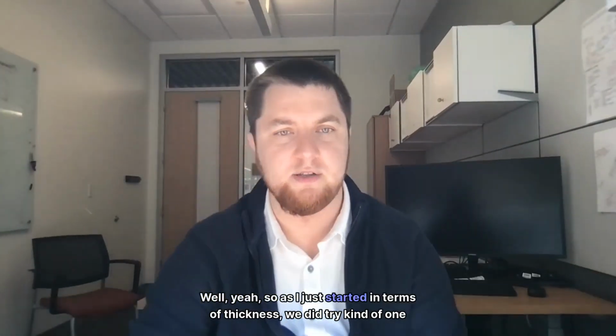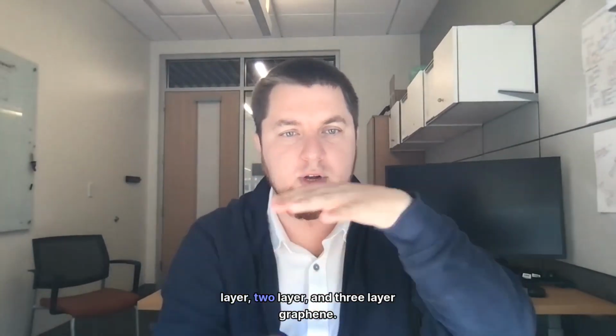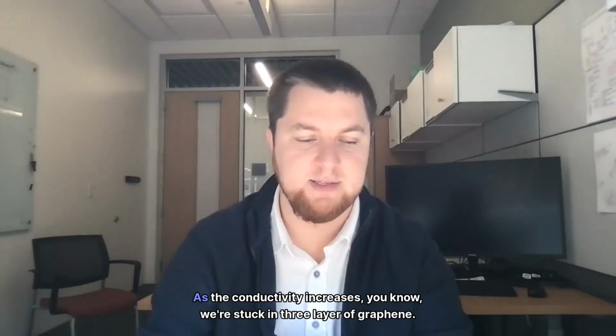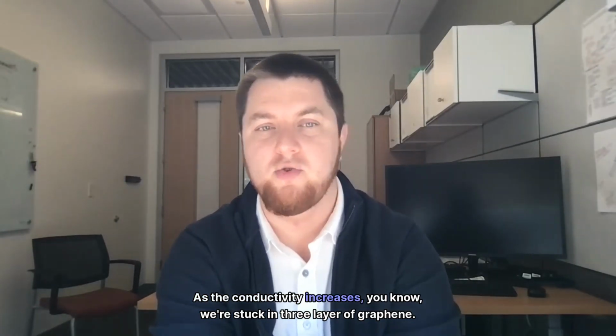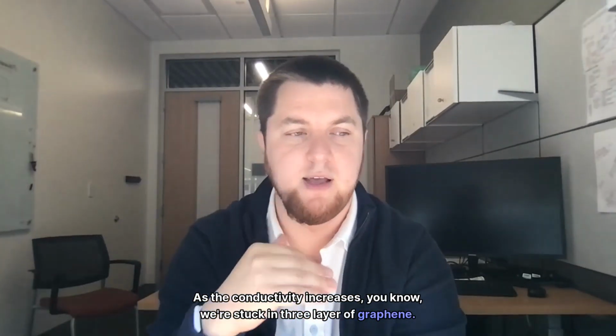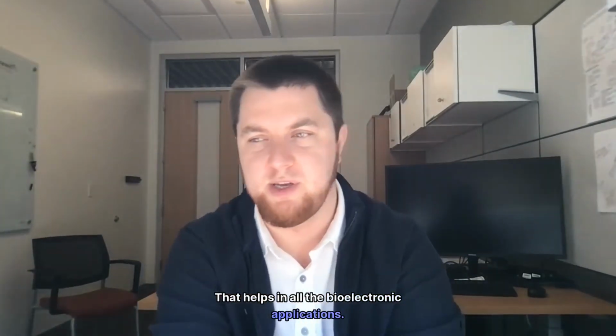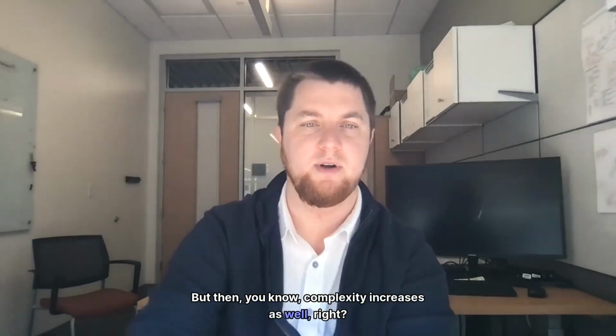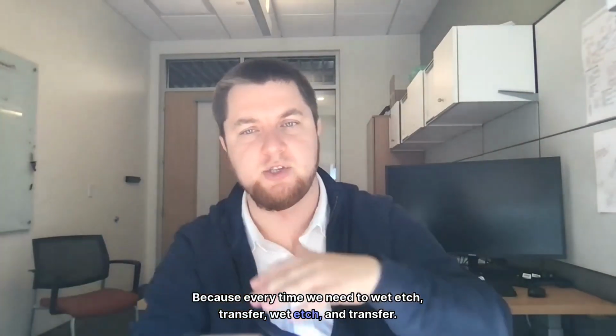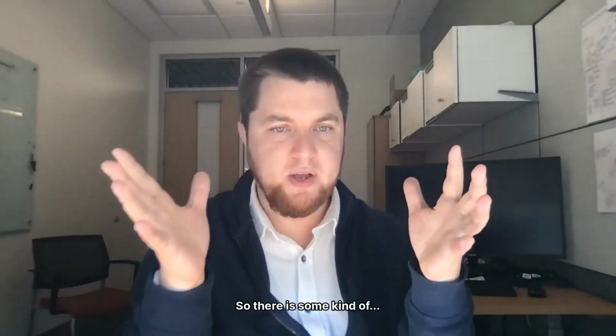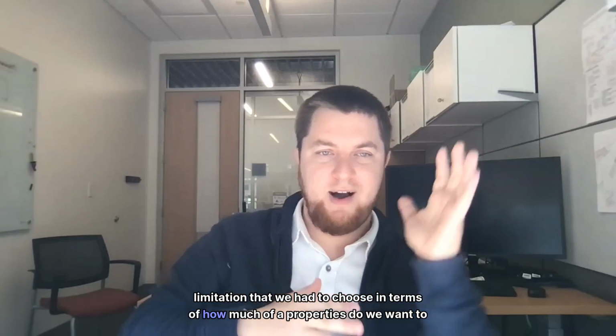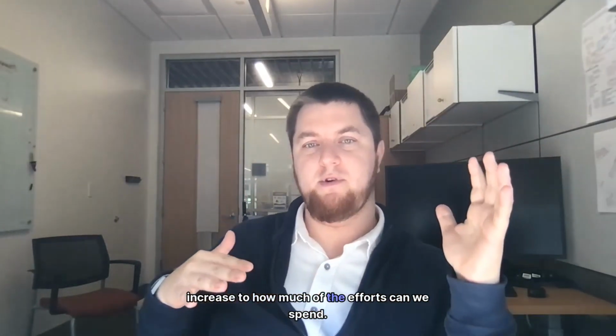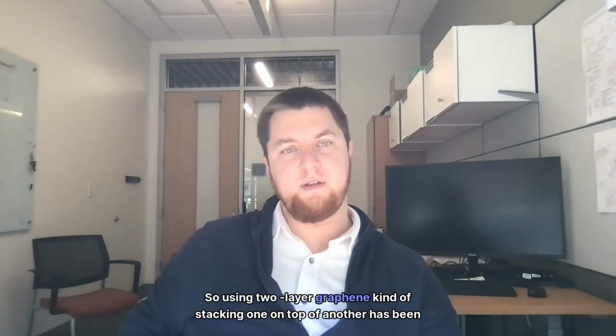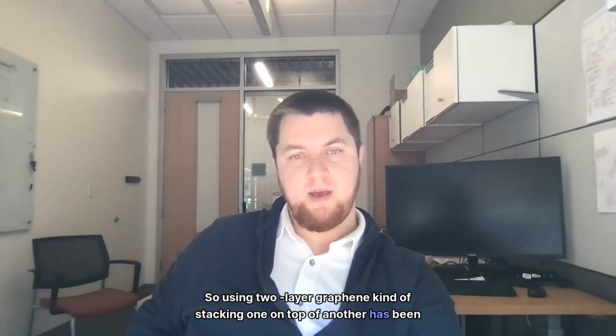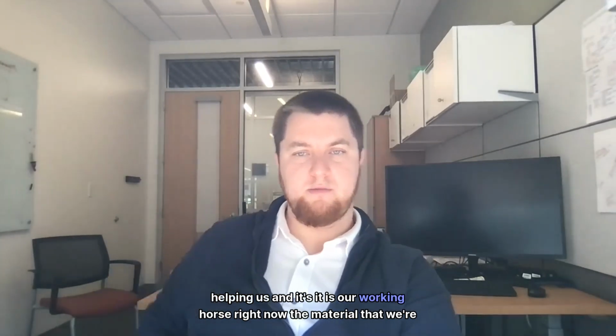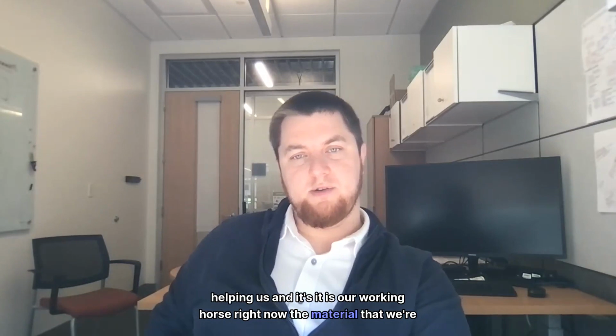Well, yeah, so as I just started, in terms of thickness, we did try 1-layer, 2-layer, and 3-layer graphene. As the conductivity increases with stacking 3 layers of graphene, that helps us. That helps in all the bioelectronic applications. But then, complexity increases as well, right? Because every time we need to wet etch, transfer, wet etch, and transfer. So there is some kind of limitation that we had to choose in terms of how much of the properties we want to increase versus how much effort we can spend. So using 2-layer graphene, stacking one on top of another, has been helping us, and it is our workhorse right now. The material that we're working with currently.